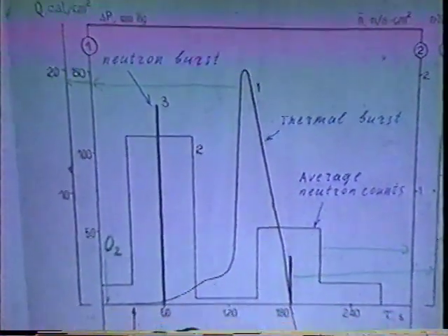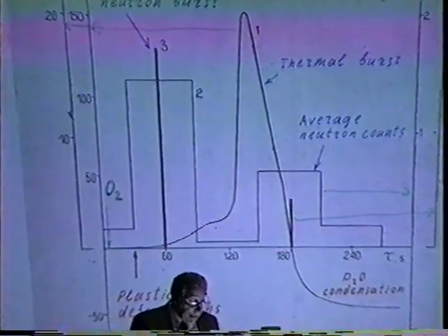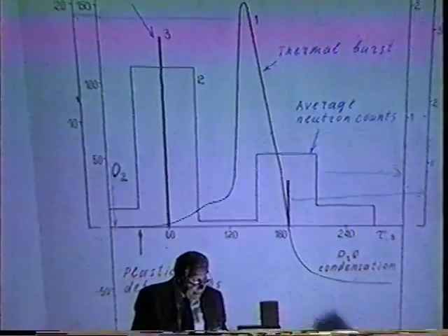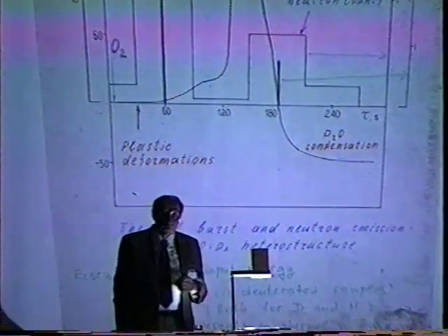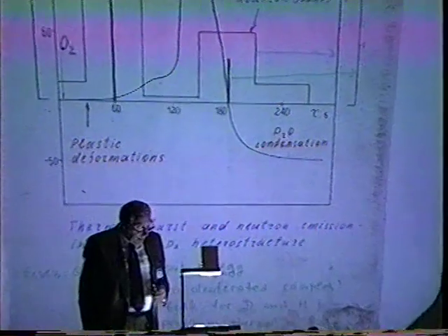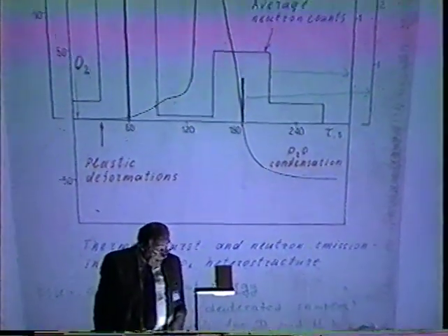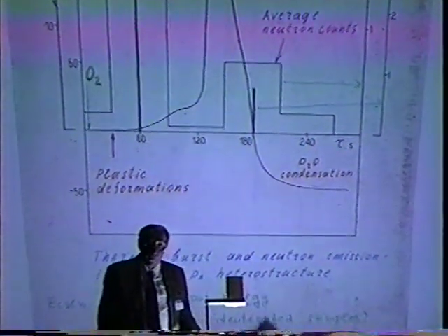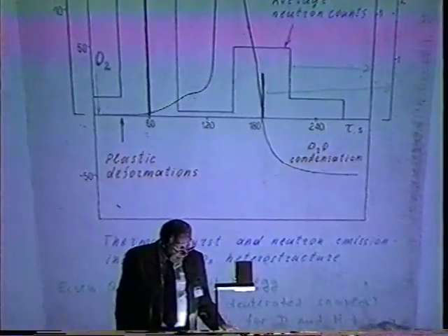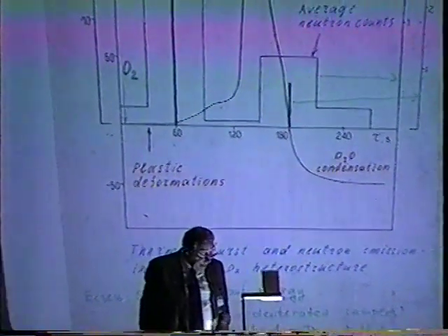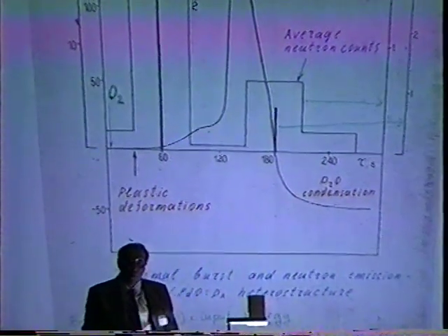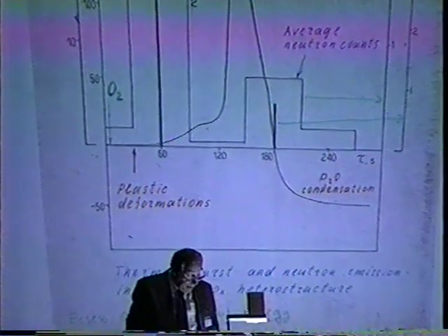Okay. Now, I already mentioned the group from the Institute of Physical Chemistry, and they also studied this type of samples, and after loading these samples and drying them, they observed 3 effects. First, some large excess heat bursts. Large means from 2 to 5 times larger than the input energy. Then they observed neutrons in the case of deuterium samples, and they also observed gammas, both in the case of deuterium and hydrogen, and also they observed some dependence of the effect on the flux of thermal neutrons, the ground flux.